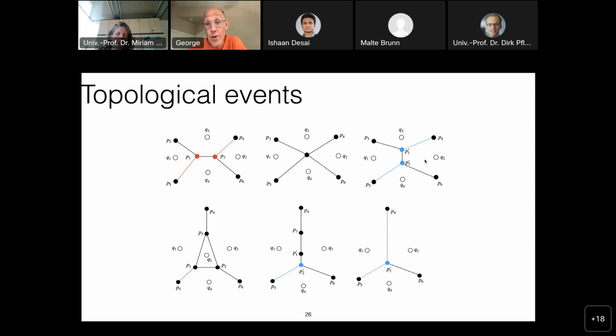But at the end now, Q1 and Q2 are neighbors, and Q3 and Q4 are not. That's an example of a topological change that we have to capture. We call this the grain neighbor switching event, because we have switching neighborhoods from Q3 and Q4 to Q1 and Q2. So this is a neighbor switch event, but we also have the grain elimination event in which this grain here completely disappears, and then we have to change the structure. You can imagine that these topological changes are quite challenging.